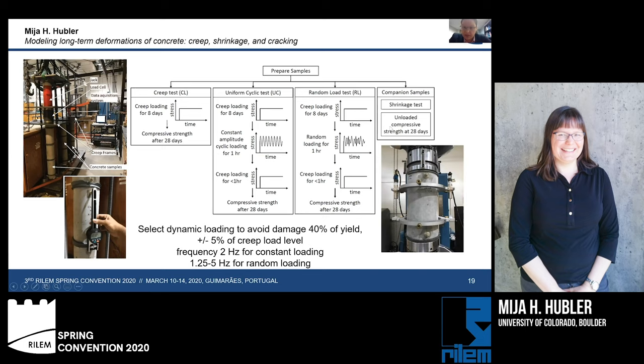The dynamic loading is conducted in a hydraulic testing machine as shown here on the right. Now we've carefully selected our dynamic loading to avoid damage. So it's at 40% of the yield. And we only allow the amplitude, both for the constant amplitude and the random loading, to vary about plus or minus 5% of this load level. For the constant amplitude loading, we are loading at a frequency of 2 hertz. And for the random loading, we range between 1.25 and 5 hertz. What this test ends up looking like is almost a humming load applied dynamically to the system.